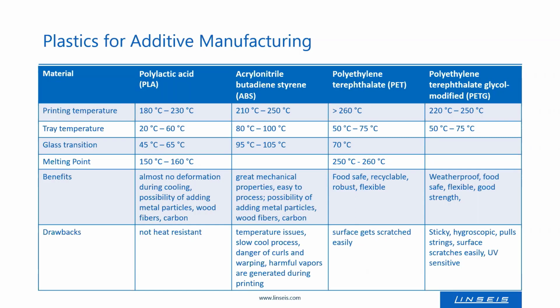And the disadvantage or the problem here with the PET is that the surface gets scratched really easily. So depending on the application, one needs to choose maybe ABS if the surface needs to be protected, for example. The PET mixed with glycol has rather similar printing temperatures and also the same tray temperature. The advantage here is that it's additionally weatherproof, so it can also be used, for example, for tools for the garden. It is also food safe, flexible, and has a good strength. But the problem with the PETG is that it's really sticky during printing. It's really hygroscopic and pulls strings rather easily. And as with the PET, the surface gets scratched rather easily. And a further problem is that the PETG is rather UV sensitive, so it's not good for applications where, for example, the sun is shining a lot.